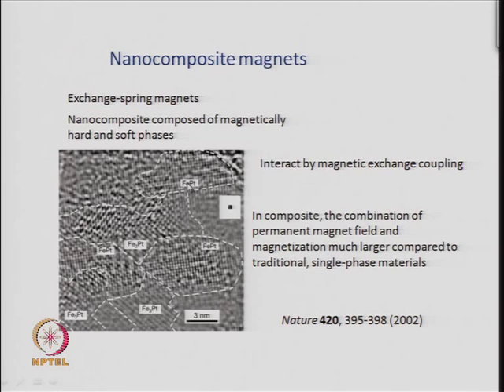This is a hard magnet, because it has a high remanent field. If you take pure FePt particles, it is a hard magnet. If you take pure Fe3Pt, it is a soft magnet, and a combination of the two, because this whole particle is around 15 to 20 nanometers on this side and 15 to 20 nanometers on this side. So, the whole particle is around 15 by 15 nanometers, and has many such small regions which are different in their properties. This part will have a different property because it is Fe3Pt, and this part a different property because it is FePt. So, this is hard magnet type, this is soft magnet type, and together they are existing.